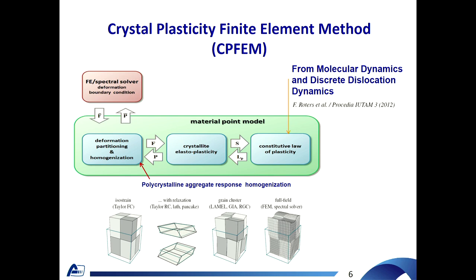For accurate calculation of mutual interaction between high explosive grains, high explosive grains and plasticizer and to account the various plastic responses of individual grains, in particular dislocation dynamics inside grain, in modeling we have to choose a method which able to account those deformation processes. Three decades ago the finite element method of crystal plasticity was proposed with aim to model deformation processes in metals and alloys where anisotropic properties of material grains play a significant role in material response. Here we apply this method to consider deformation process in high explosive.